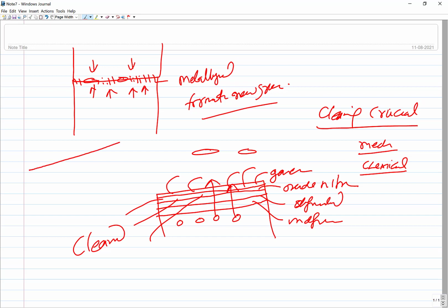So when you have one clean surface and another clean surface, and the two are brought in contact with each other, then you have at least a fair playing field for atoms to move from one side to another, because now there is no air gap, and there are no impurities in the form of gases, oxides, nitrides and so on and so forth. So this diffusion only will help to form the new grains and develop the metallurgical joint. So I hope now,